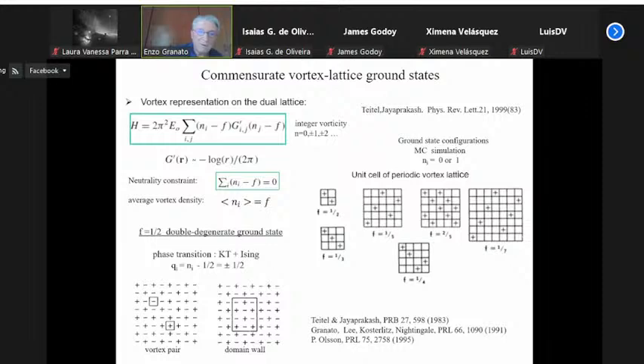Now, the ground state of the vortex configuration has been studied by this seminal work by Teitel and Jayaprakash, which shows that if you write the Hamiltonian of the system in terms of the phase, it can also be written in terms of the vortices. And these vortices, as I just mentioned, interact logarithmically. So the Hamiltonian you get in the vortex representation is a sum over all pairs of these vortices interacting logarithmically. And the frustration here arises as a background constraint, such that the sum of the vorticity minus f should be equal to 0. This translates into the equation that the average number of vortices is equal to the frustration, and the frustration is fixed by the magnetic field. This basically is just saying that the number of vortices is proportional to the flux created by the external magnet.